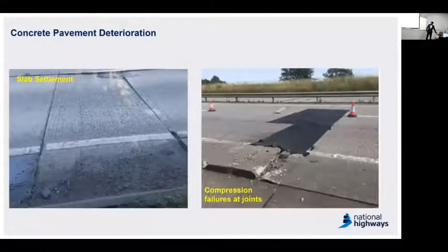The other type you could think about is something called slab settlement. Again, you could expect to have maybe a void underneath your concrete pavement, or it could be a drainage issue that causes these sorts of things, and even dowel bar issues. There is quite a combination of reasons that could possibly lead to these sorts of defects. And this one is compression failure at the joint.